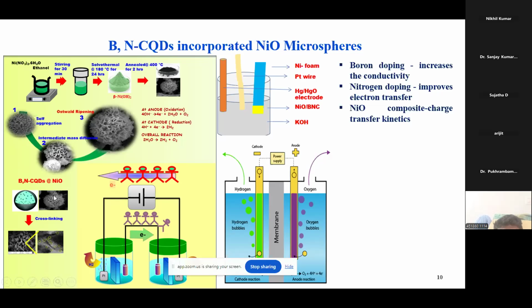Then with this one, I did two works, like supercapacitor as well as total water splitting, OER and HER. When I'm doing this incorporation, B and CQD are formed separately, then we did the cross-linking method. While we get these microspheres, we incorporated the B and N doped CQD. It's below 10 nanometers, so we can incorporate it into any porous substrate, any porous structure. So we can get an enormous amount of output.